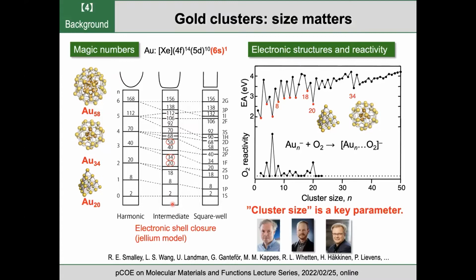So electronic structure is very important when you talk about the stability of gold clusters. This is the lesson we have from the gas phase studies. And chemical reactivity can also be explained by the electronic structures. For example, the reactivity against oxygen molecules can be explained by the electronic shell. So from these studies, we understand we must control the cluster size with atomic precision. Otherwise, we cannot say anything about the structure-property correlation. So this is the mission we have to achieve. Okay, atomically precise synthesis is necessary.